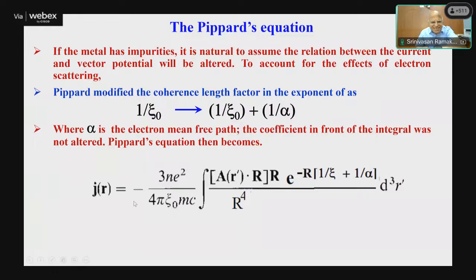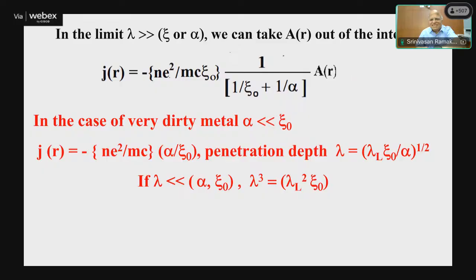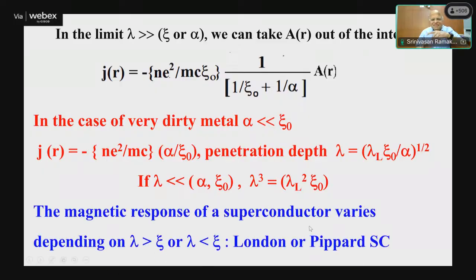And so is the JR, which is given by this expression. So he was able to explain the penetration depth, which we saw as a function of impurities, using this expression. So that's how we realized that he was right. So we have two kinds of superconductors. One is called the Pippard superconductor, where the coherence length is greater than lambda, and there is a London superconductor where the penetration depth is larger than the coherence length.